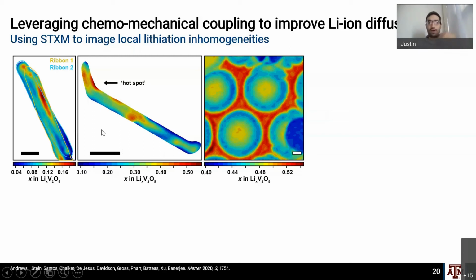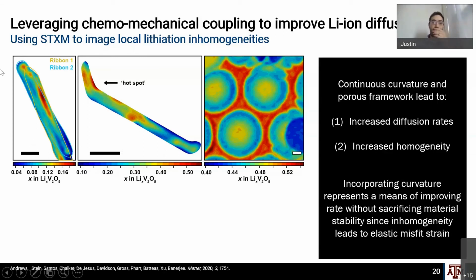And so there's something about this continued curvature. One conclusion that we can draw from this is that in the case of the bent nanowire, the material that is bent and under compressive strain lithiates much more quickly at that space. So strain can actually be applied to lithiate these much more quickly. But when we have a single point of strain, the issue is that it leads to much faster rates of lithiation at that point, which can lead to even greater inhomogeneity than in straight nanowires.